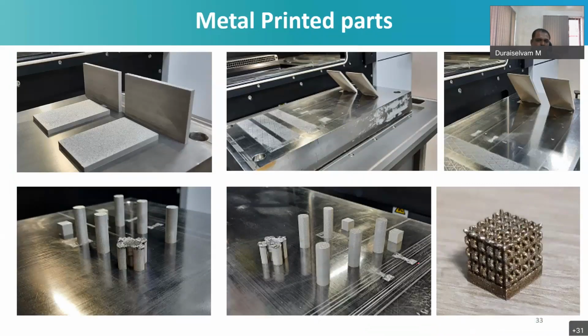And these are some of the metal prints we have done in recent times, just simple solid blocks that we printed earlier. And here we printed the same block with a 45-degree inclination and without any support structure. You can see that here we don't use any kind of support structure, and up to 45 degrees you don't need a support structure. The powder itself will support it, and when the angle is more, then definitely you need a support structure. And some simple cylinders that we have printed.